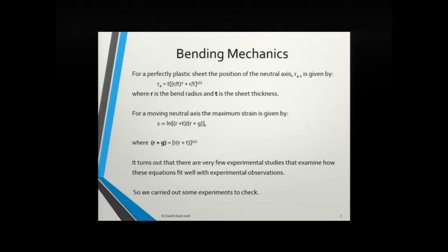It turns out, about 30 years ago when we started looking at this stuff, or 20 years ago, I exaggerate, that there were very few experiments that had actually looked at how well these equations performed. How close to experimental results were they? And since we were using these equations for a variety of things, I decided that we should actually check them out. We found a paper by Brendan Parker in Australia at Monash about 20 years ago, where he'd used hardness measurements. And he had shown that the neutral axis moved, but the technique had too low a resolution to be able to compare with experiments.